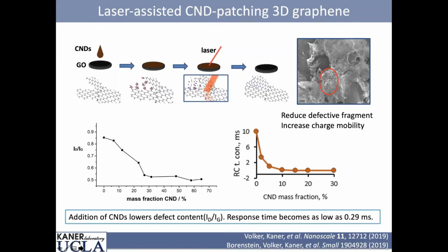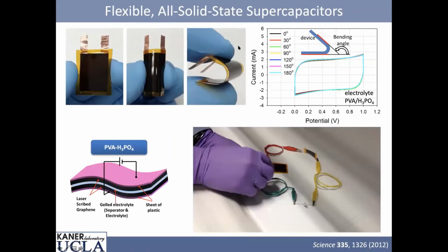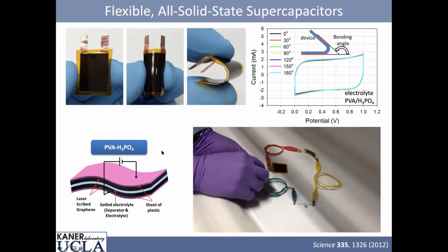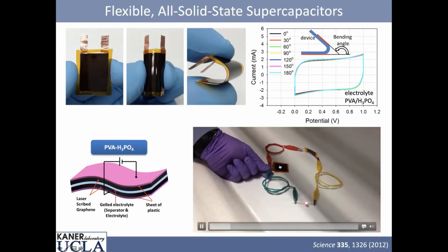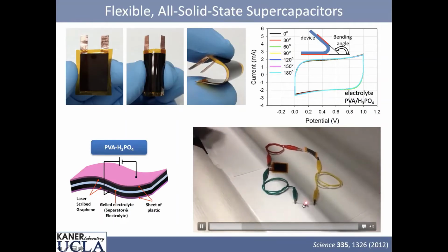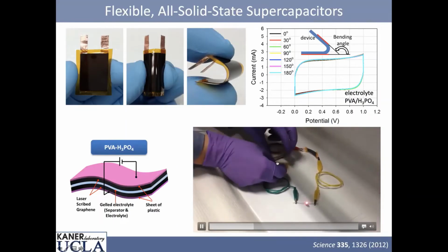Okay, so we can get down to 0.29 milliseconds. Now, going back to our supercapacitors, we can make very flexible supercapacitors. This is a current potential. We're simply running this experiment, and what you'll see is as we flex this, the curves overlap with each other. We made a little movie just to show how flexible these are. We charge this up for a few seconds, we can run an LED, and now we're going to flex this graphene supercapacitor, and you'll see it doesn't affect the LED.